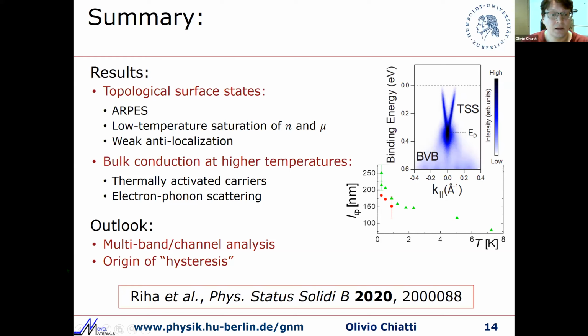What is left, the challenge for our outlook, is that we probably need to apply a multi-band channel analysis to get a better idea what the conduction is at lower temperatures, which needs magnetotransport measurements at higher fields. And we have left to work out what is the origin of this sweep-rate-dependent hysteresis.